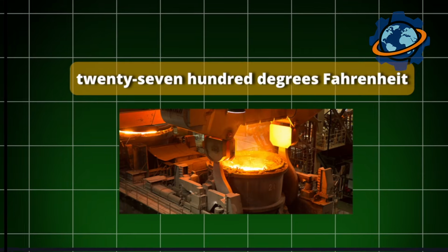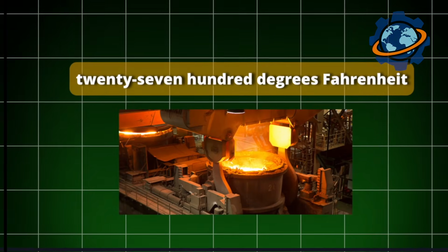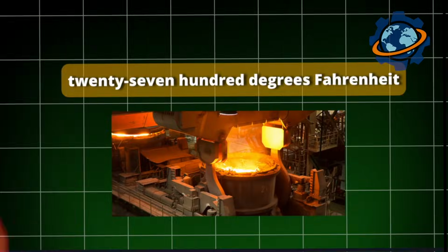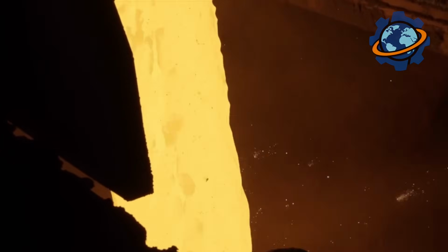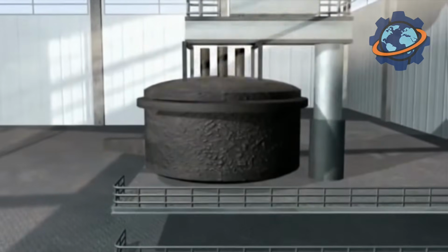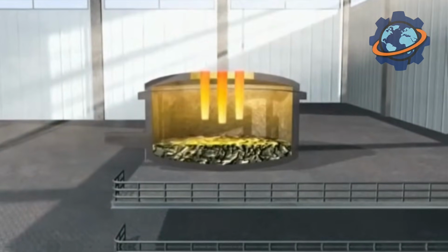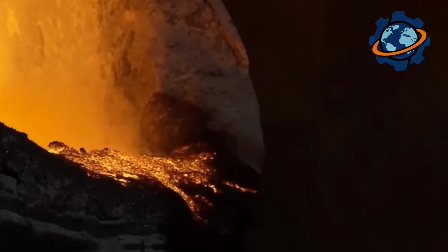Pig iron temperature at the furnace bottom is 2,700 degrees Fahrenheit. It glows blindingly white with an orange tint. Pig iron is denser than slag, so it stays at the bottom. Slag, molten impurities and fluxes, floats on top. Every 4 hours, they open the tap hole, an opening in the furnace's sidewall.